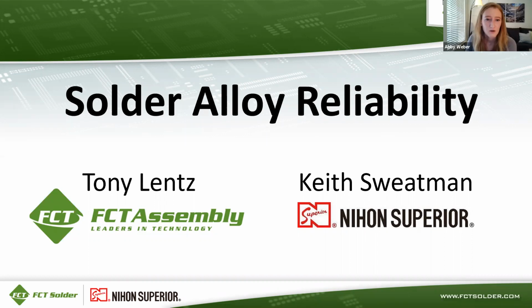Thank you, Tony. Are there any other joining materials that can be used in electronic devices besides solder? Yes, there are. Actually, there are sintering materials which are becoming more popular, not necessarily for component soldering to PCBAs, but for interconnect electronics. Sintered materials don't have to be heated past the melting point, which is good because they're using metals like copper or pure silver, which have very high melting points. And so they're able to put those materials onto the interconnect, heat them enough to where they sinter or bind together, and then they form an electrical connection and a pretty strong mechanical connection for that solder joint.